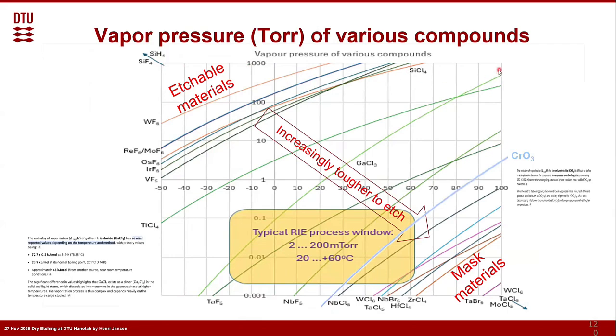And so it's 750 torr. Then here you see the temperature in degrees Celsius. So starting from the boiling temperature, or the boiling point, for instance for tungsten hexafluoride, which is around, let's say, 25 degrees at room pressure. If you then go to a lower pressure, we just follow what we did logarithmically before with water. We follow the enthalpy of vaporization. So we just follow Trouton's law together with the Clapeyron equation. And it goes like this.